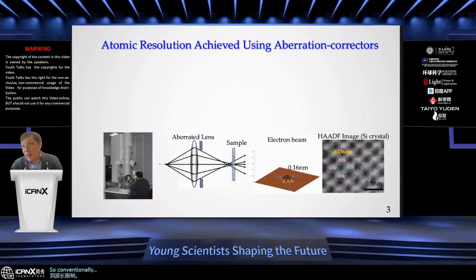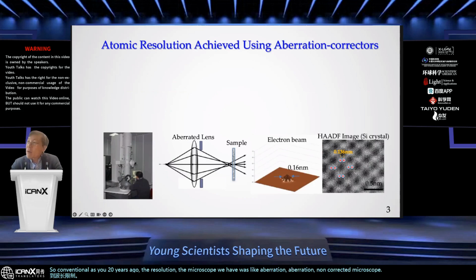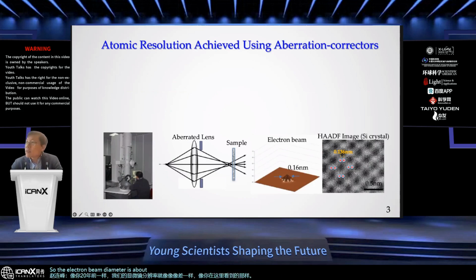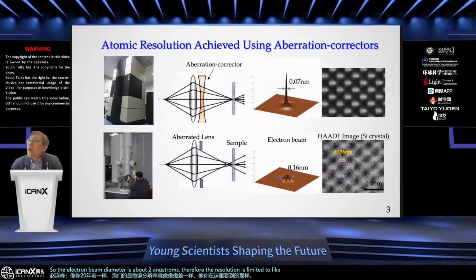Conventionally, 20 years ago, the microscope we had was an aberration non-corrected microscope, as you can see here. The electron beam diameter is about 2 angstrom. Therefore, the resolution is limited to about 0.2 nanometer. When the aberration corrector was introduced about 20 years ago, the resolution went all the way up to 0.07 nanometer, and at that time you were able to distinguish the dumbbell in the silicon crystal.